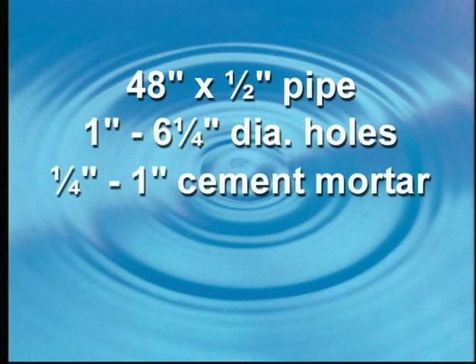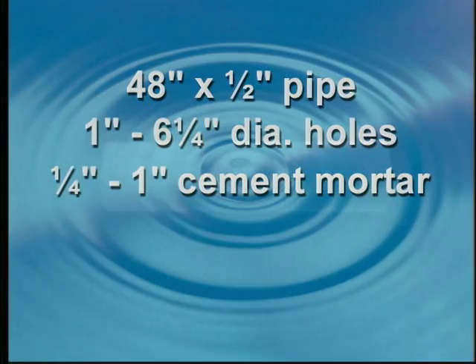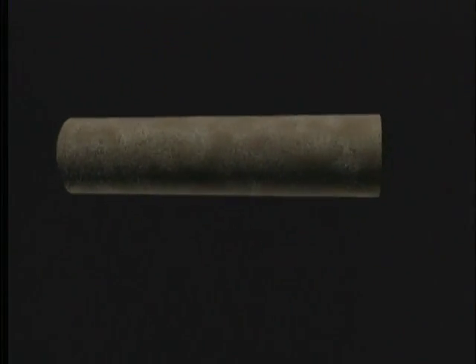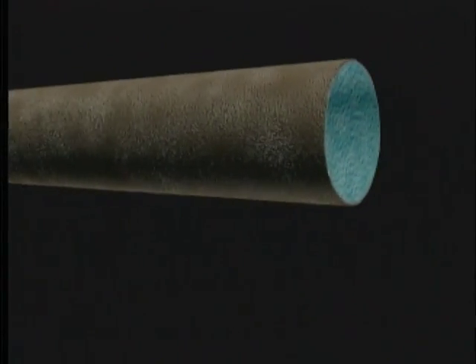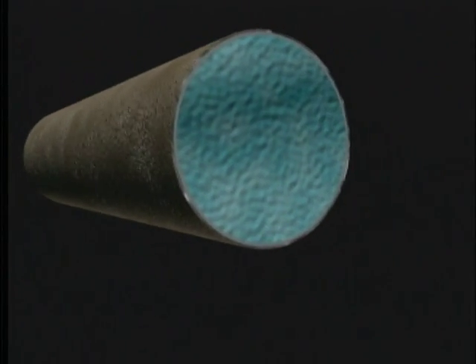Cement mortar lining was then centrifugally applied to the inside of the pipe, the thickness of the lining graduating from 1/4 inch at one end to 1 inch at the other. After an adequate curing period, a prescribed hydraulic testing procedure was followed to determine at what pressures failure might occur in the cement mortar lining.